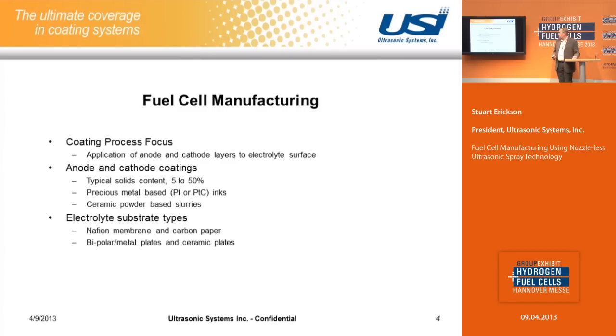With regard to fuel cell technology, we're primarily concerned with applying the catalyst to the electrolyte substrate. And that really means the anode and cathode layers. These catalysts can be precious metal-based carbon type catalysts. They can also be ceramic slurries. They can be other proprietary materials. And the solids range can be anywhere from the low single-digit solids content all the way up to about 50%, depending on the material. For electrolyte substrates, we can spray on the Nafion membrane, on the carbon paper substrate, or onto bipolar metal plates and ceramic plates.